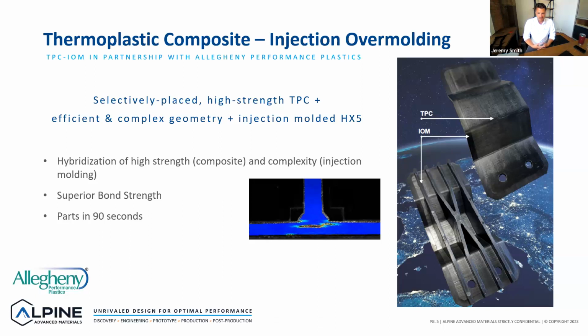What we're doing here is getting an extremely high strength property out of the unidirectional tape, but utilizing the manufacturing benefits of injection molding, so we can get more complex shapes in a much quicker process, as opposed to going through the process to do high layups or pre-preg carbon fiber materials. The manufacturing process for them can be cumbersome to get complex geometries. This process marries both and can produce parts in about 90 seconds, typical injection molding cycles. What we've seen with the HX5 material is a superior bond strength with the unidirectional tapes. In our most recent test, we actually showed delamination of the tape prior to delamination of the bond between the HX5 material and the unidirectional tape. So that's a superior bond strength.